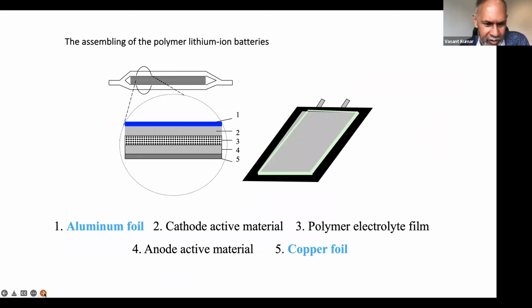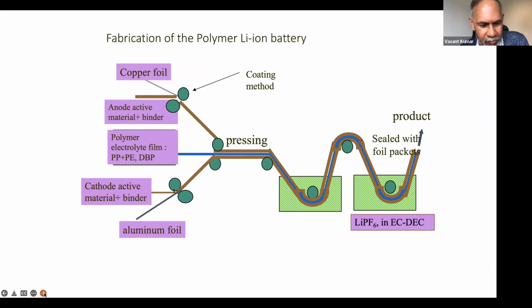Practically speaking, the battery devices are very simple to look at. It has aluminum and copper foil as current collectors, a cathode active material, a polymer electrolyte or a separator filled with liquid electrolyte, and an anode active material. The assembly line is well developed now, and they have to be in very dry conditions, controlled clean rooms. So for large scale production, the capital costs are quite expensive. All the machinery is readily available from many sources, and any new battery chemistry that comes up, if it is able to use the existing known technology and assembly line, will fast track its development.